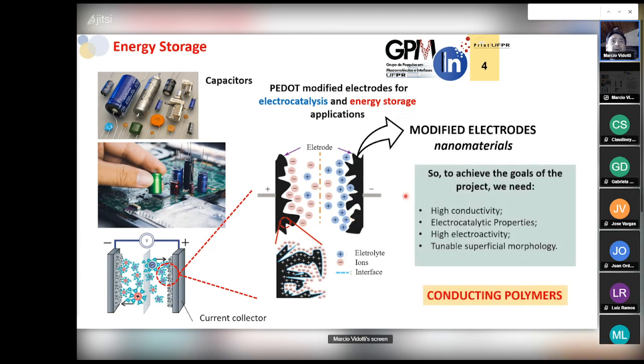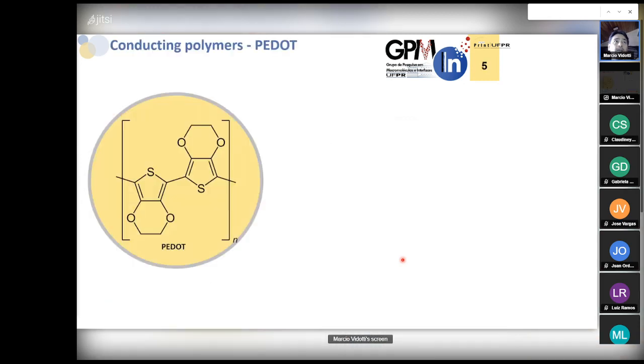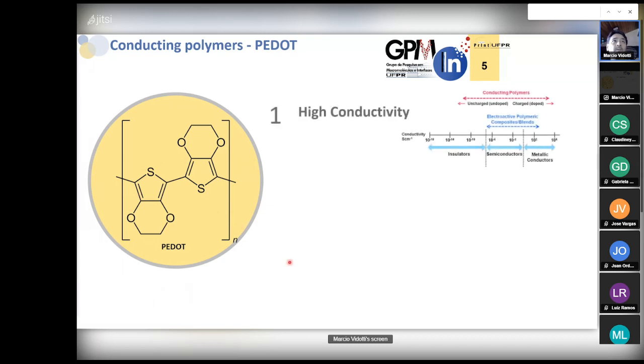So in this project, we have used the conducting polymer, PEDOT, which has high conductivity, electrocatalytic properties, electroactivity, and it's possible to modify any kind of substrate. And just a little bit more detail about PEDOT. Here I'm showing the chemical structure of the polymer, which has, as I said, high conductivity. And the mechanical properties of the conducting polymer are quite important, because we can change any kind of substrate with this polymer. For example, in this work, we have used some flexible electrodes, which is very important for energy storage, but also we have used some diamond electrodes, which is very important as well for electrocatalysis.